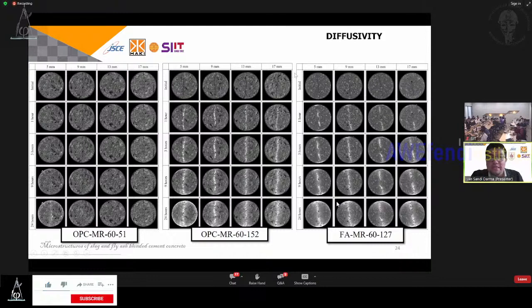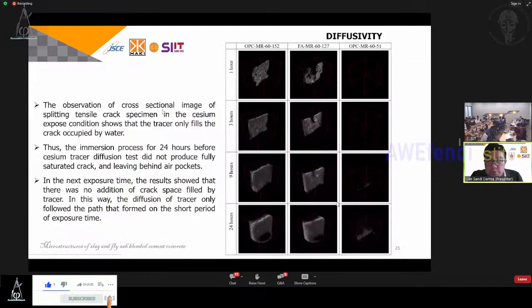Okay, this is thresholding. The observation of cross-sectional image of splitting tensile crack specimen in the cesium exposed condition shows that the tracer only fills the crack occupied with water. Thus, the immersion process for 24 hours before cesium tracer diffusion test, unfortunately, did not produce fully saturated crack, leaving behind the air pocket. In the next exposure track, the results showed that there is no additional crack space filled by the tracer. In this way, the diffusion tracers only follow the path that formed in the short period of exposure time.